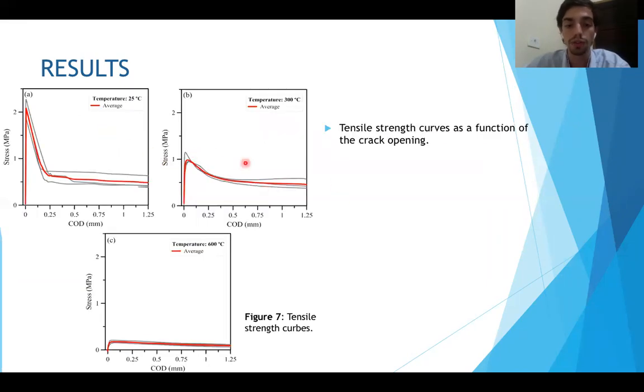Here are the tensile strength curves as a function of crack opening. The 3 interesting points to note are the peak resistance, the crack opening at 0.5 millimeters and 1.25 millimeters, which characterize the SLS and the ULS respectively. We see the curves at 25 Celsius degrees, 300 Celsius degrees, and 600 Celsius degrees. At 600 Celsius degrees, there is practically no peak.